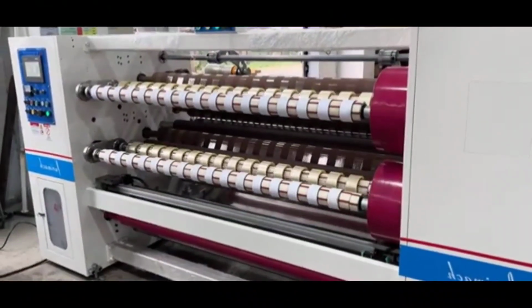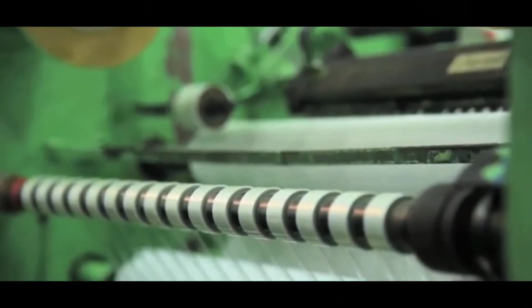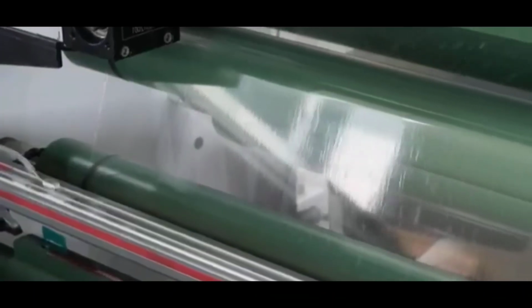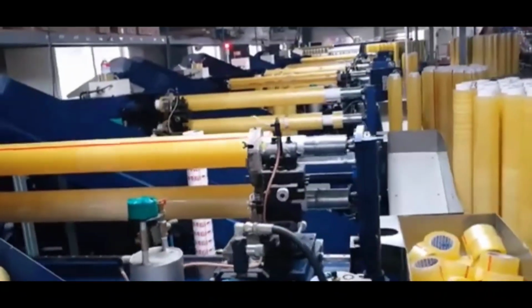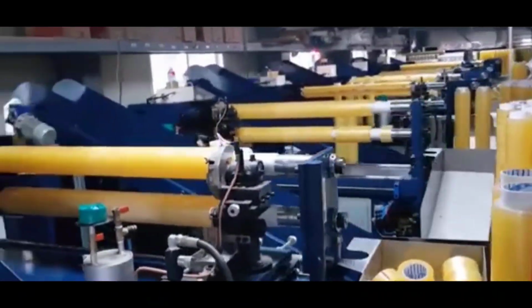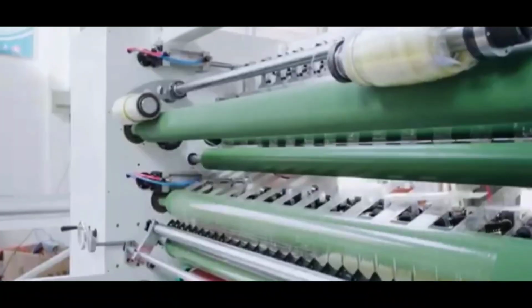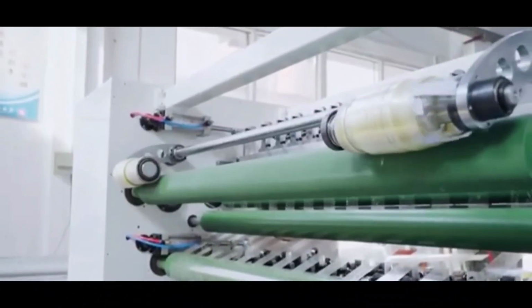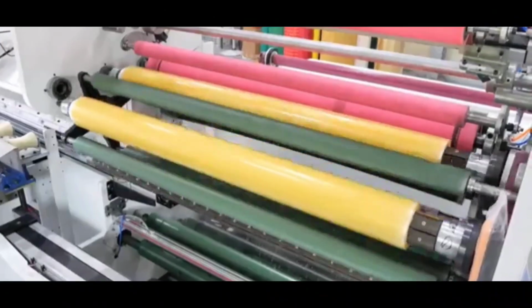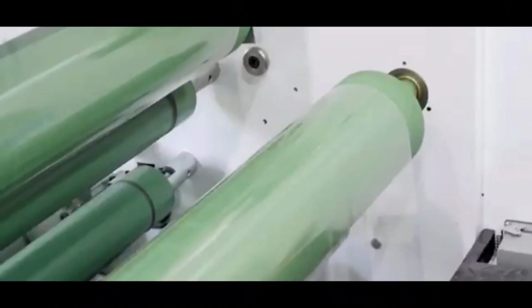If tension exceeds 3 to 4 psi, the film can stretch and distort the adhesive surface. If it's too low, the winding becomes loose and prone to peeling. As the machine starts, an air pressure nip roller lightly presses the film against the core, ensuring a uniform bond as the adhesive layer wraps around.